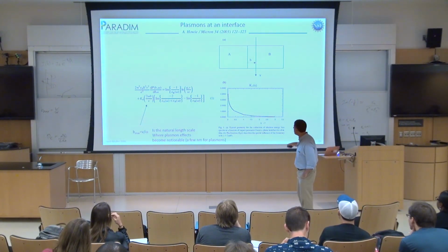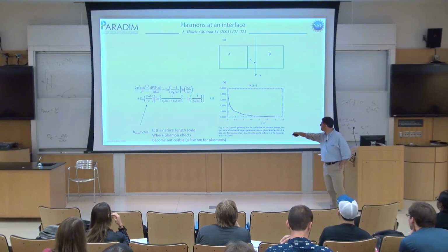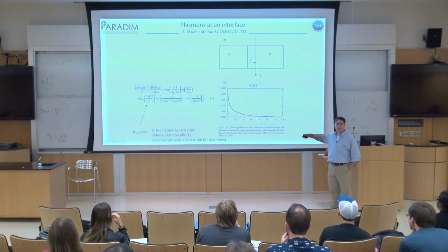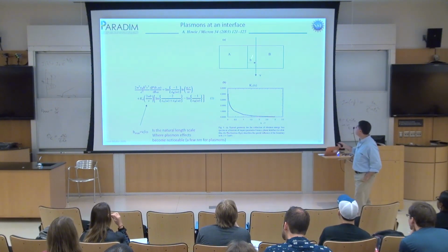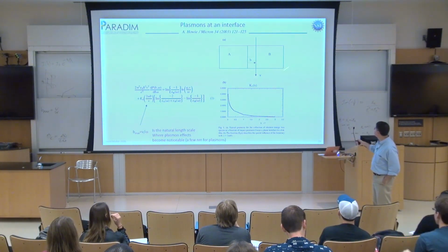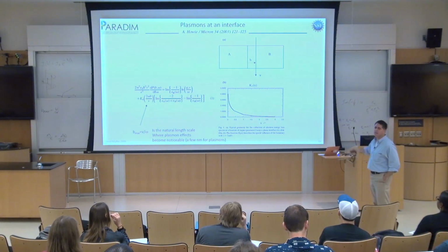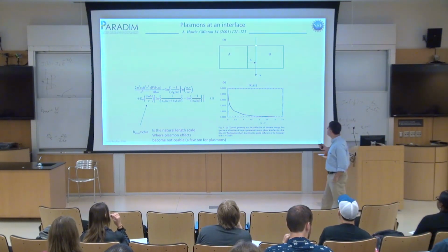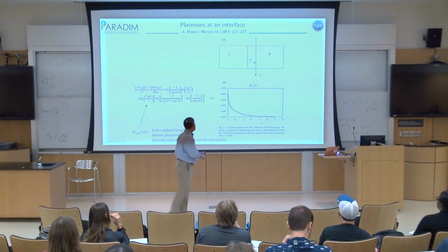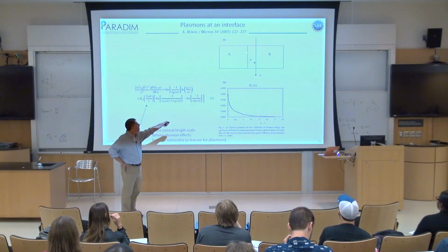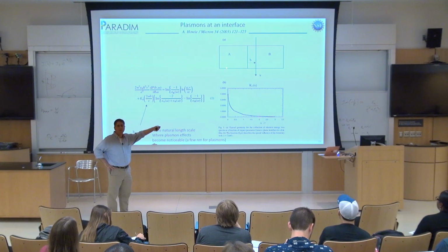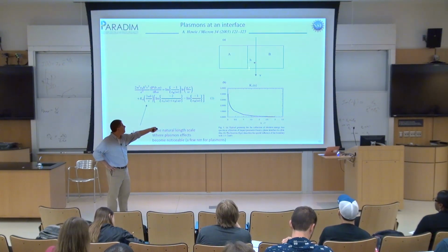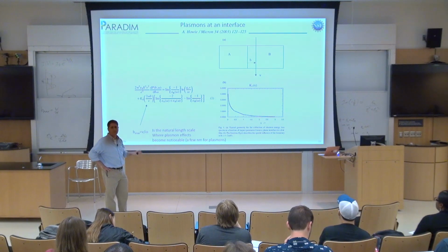The K0 Bessel function decays exponentially at large distances, and it diverges logarithmically at small distances. That's the shape of this curve. So what I expect is any EELS of an interface comes up exponentially, and then it gets really big at the interface. And the problem with this is, notice that in this model, I haven't allowed for any possibility of bonding at the interface. All of these effects I see are based on the different dielectric responses of the two bulk materials. There's no interface information in this at all, at least from a materials perspective.